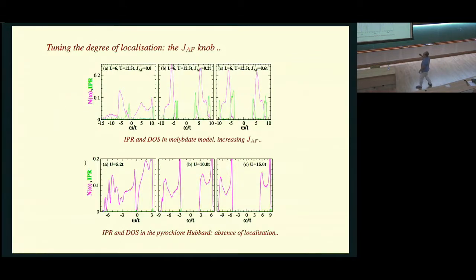So JAF seems to play an important role in the increased localization of this. Now you could ask, but you had a spontaneously disordered metal in the old pyrochlore. The old pyrochlore led to scattering and finite resistivity. But if I look at the IPR in the old pyrochlore Hubbard model, not this orbital spin business, I see nothing indicative of any localization. So it turns out, within the calculations and all the caveats, that the molybdates model represented by spin and orbital fluctuations seems to have localization effects induced by the interactions in the problem, while just the Hubbard model does still have a finite resistivity phase and spontaneous disorder, but nothing that can quite be called Anderson localization of the electrons in it.